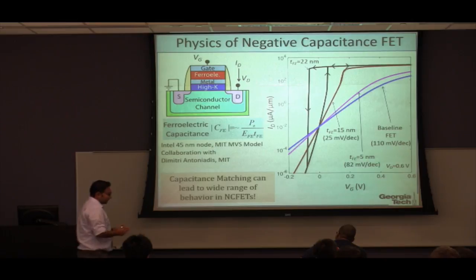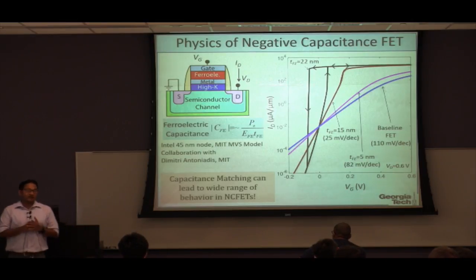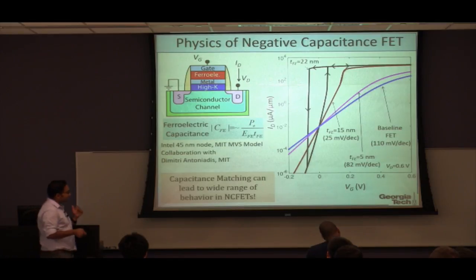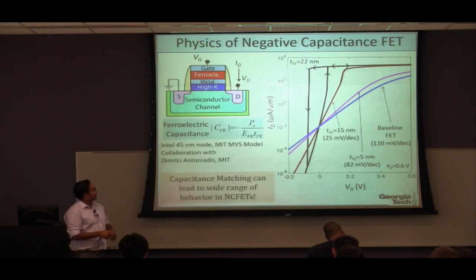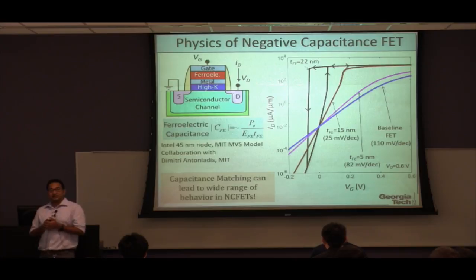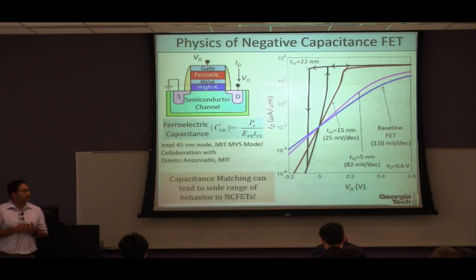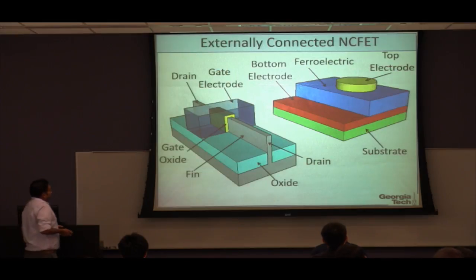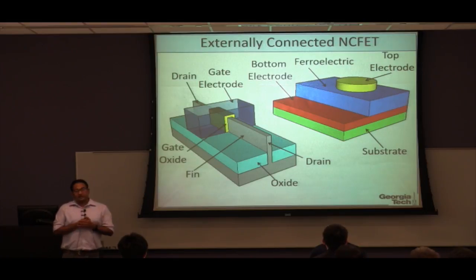So the bottom line is that starting from a small value of ferroelectric thickness, as you increase the thickness, your subthreshold swing decreases, and at some point you will get a hysteresis in the current voltage characteristics of the device. All right, so now what we did was a very simple experiment.